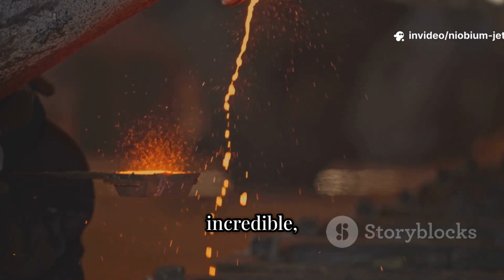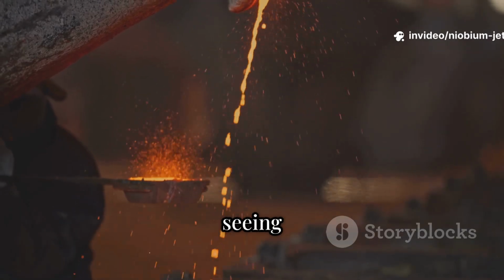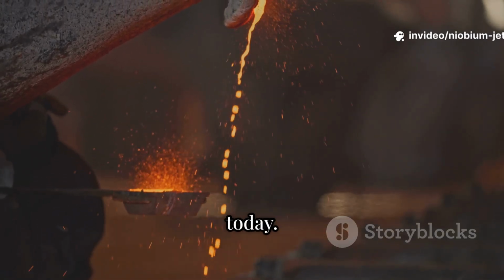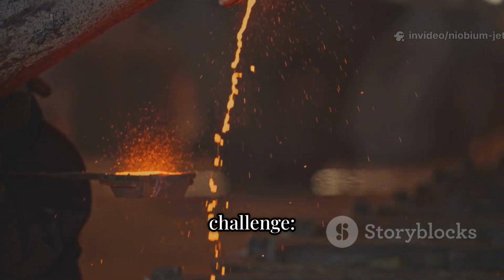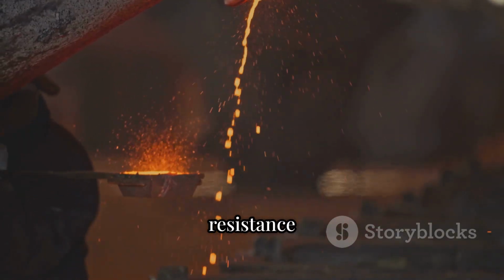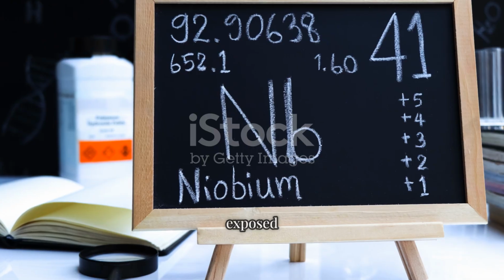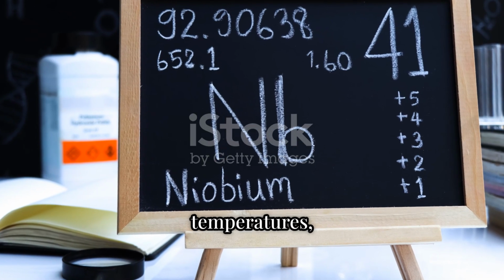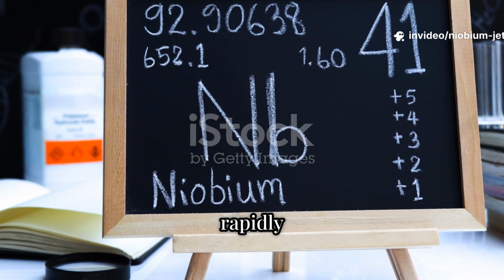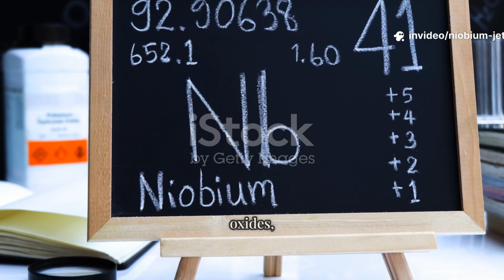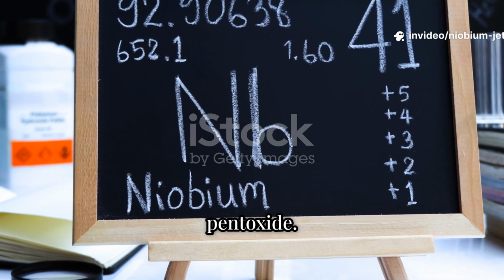This all sounds incredible, right? But there's a reason we're not seeing niobium in every jet engine today, and it's a critical challenge. It's poor oxidation resistance at high temperatures. When exposed to oxygen at high temperatures, niobium reacts rapidly to form bulky, non-protective oxides, primarily niobium pentoxide.